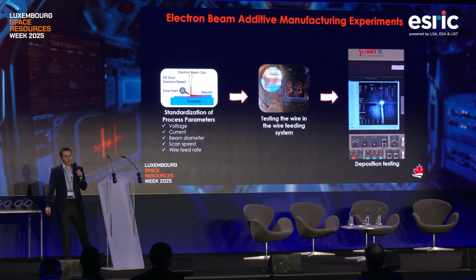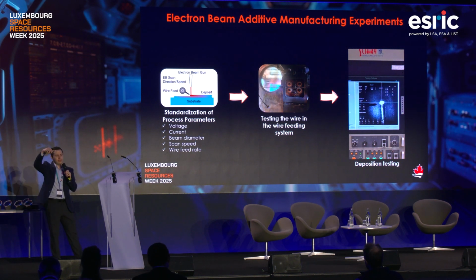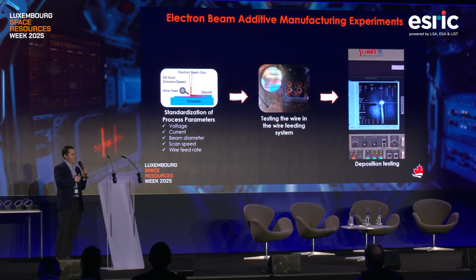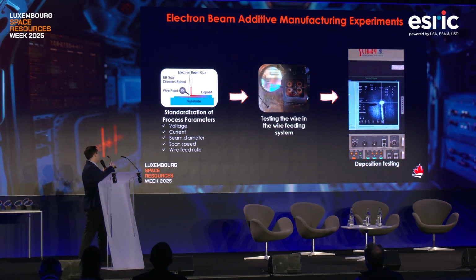And then the last part is electron beam additive manufacturing. We're using electron beam additive manufacturing to produce something with that wire. Basically, we worked on standardizing our process parameters. With electron beam, you have an electron beam. It acts directly into the aluminum. It melts it, and then you can deposit it into a build plate. Some of the variables that we have to control were the voltage, the current, the beam diameter, the scanning speed, and the wire feed rate.